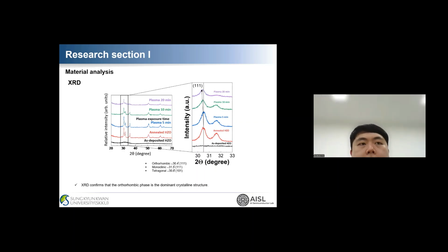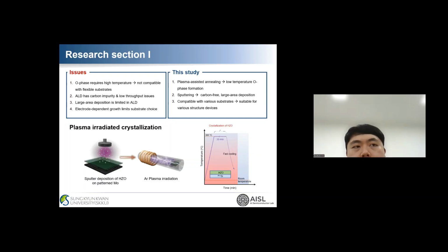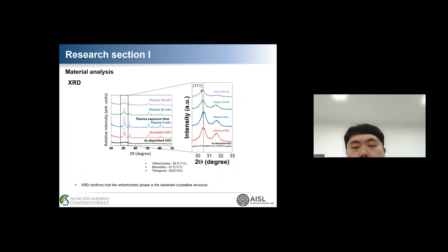In the following slide, I will compare two material properties and explain the mechanism behind the low temperature formation of the orthorhombic phase. First, we performed crystallographic analysis using XRD. For the argon plasma treated samples, the XRD peak gradually shifts toward 30.4 degrees, which corresponds to the orthorhombic phase, as the plasma exposure time increases. At the same time, the peak associated with the monoclinic and tetragonal phase decreased. This indicates that plasma-assisted crystallization stabilizes the orthorhombic phase, which is responsible for ferroelectricity.